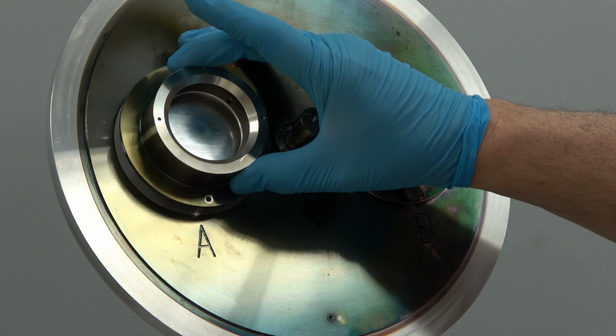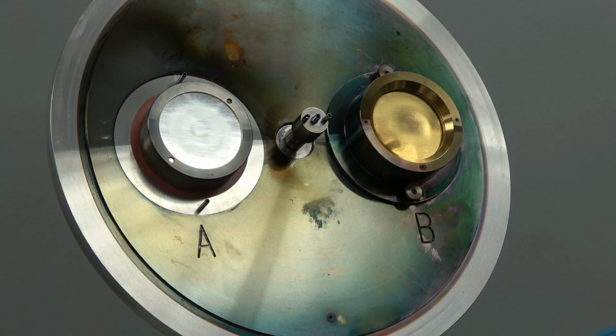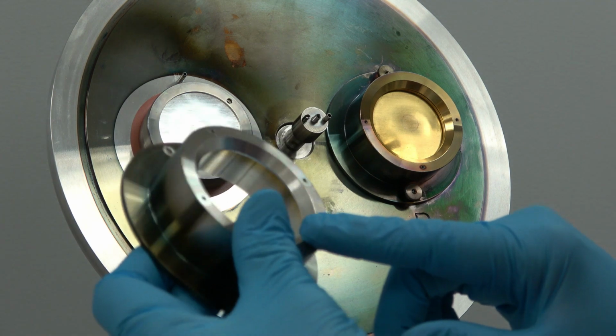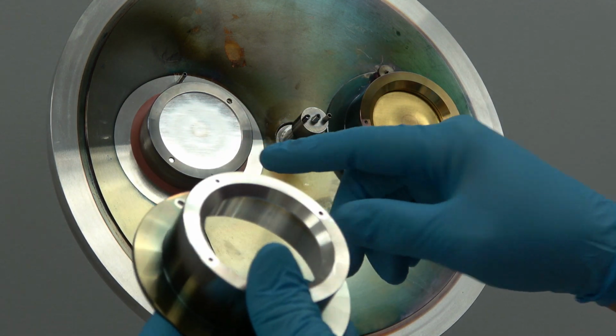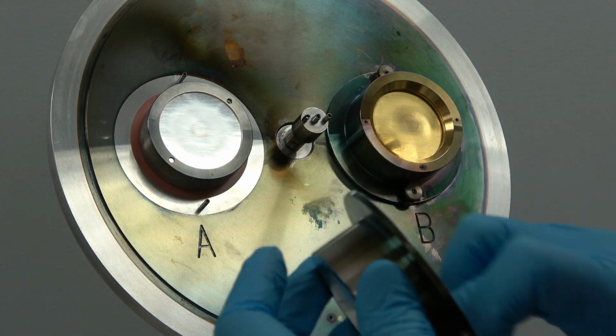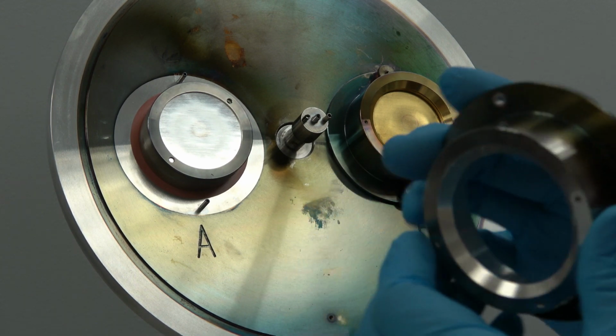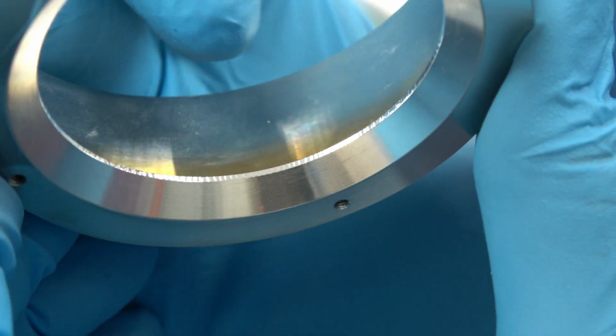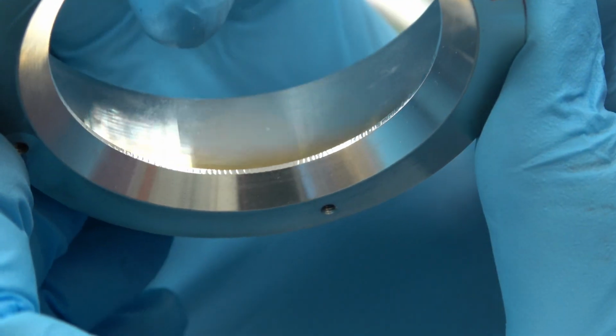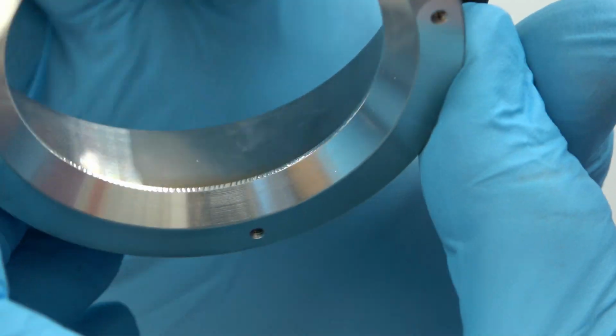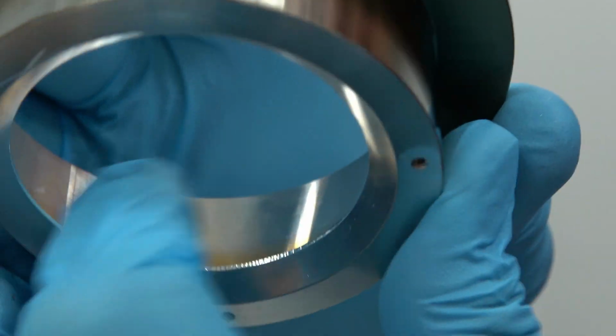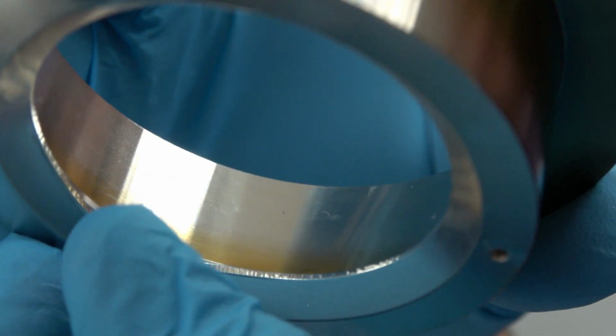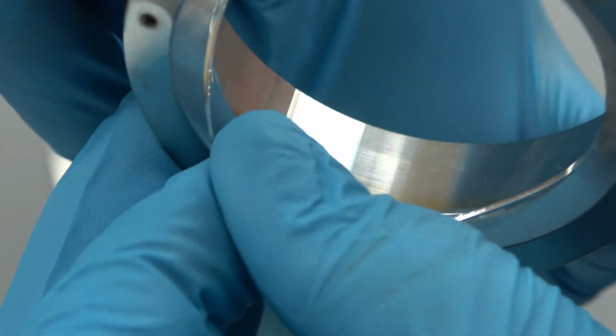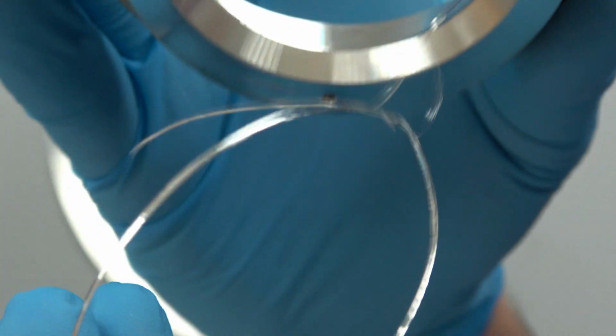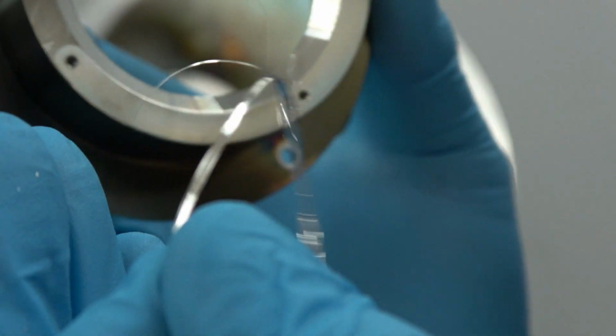Those nuts hold the dark space ring, which is at a different voltage potential compared to the target. This is the part that you need to periodically keep clean, because I don't know if you can see this real well, but there's little ripples along the edge. This is chromium that's not adhering to the aluminum of the dark space ring, and as you can see, I've pulled off sputtered material from the inside.